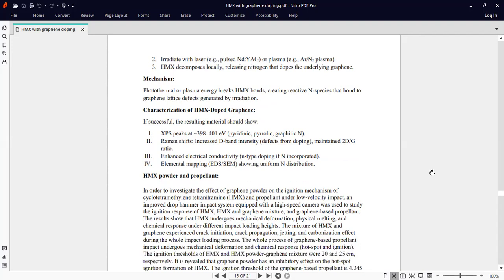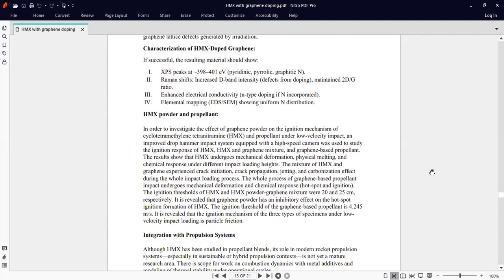The mechanism of this reaction is that photothermal or plasma energy breaks the HMX bonds, creating reactive N species that bond to graphene lattice defects generated by irradiation. If successful, the resulting material should show XPS peaks at 398 to 401 electron volts, and a Raman shift with increased D band intensity, which is defects from doping, while maintaining the 2D to G ratio, enhanced electrical conductivity, and n-type doping. If nitrogen is incorporated, EDS or SEM elemental mapping should show its distribution.